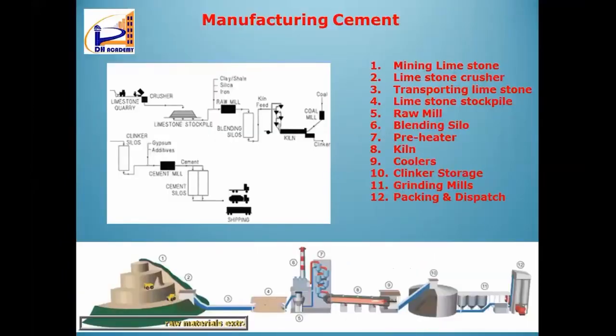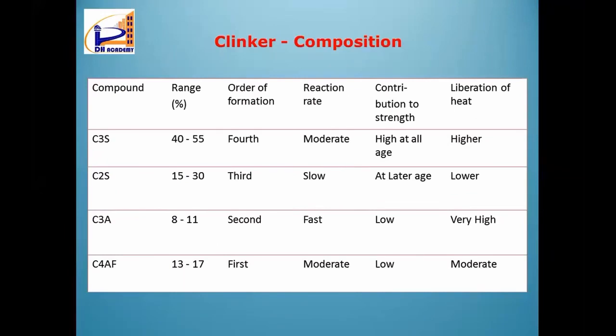The manufacturing process, time is not there, so we are not covering it. And these are called Bogue's compounds: C3S, alite, C2S, belite, C3A, celite and C4AF, ferrite. C3S is more in concrete, and it is mainly responsible for early strength and strength at all stages, but the problem is higher heat generation. C2S means belite. It is 15 to 30 percent. At a later age it will contribute.